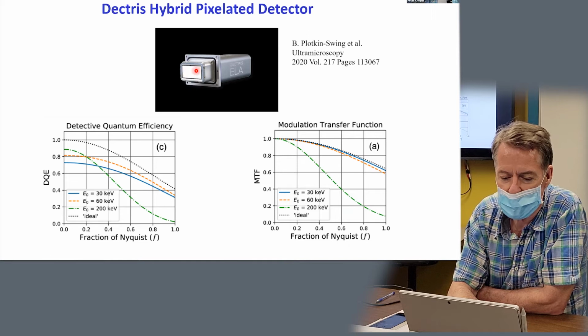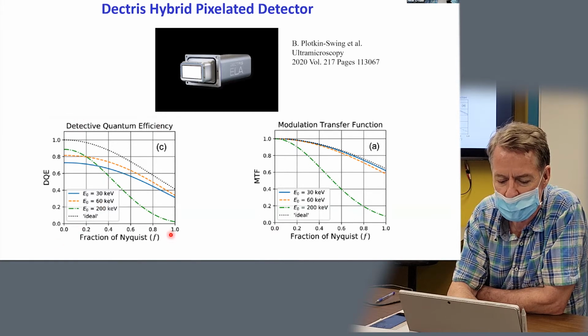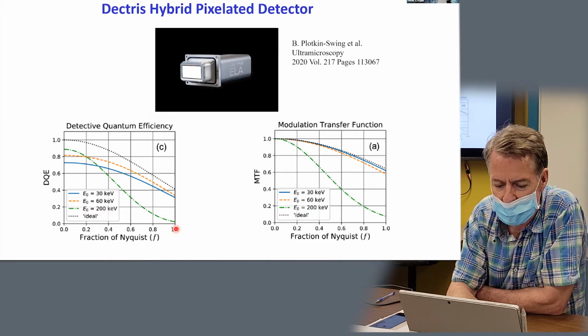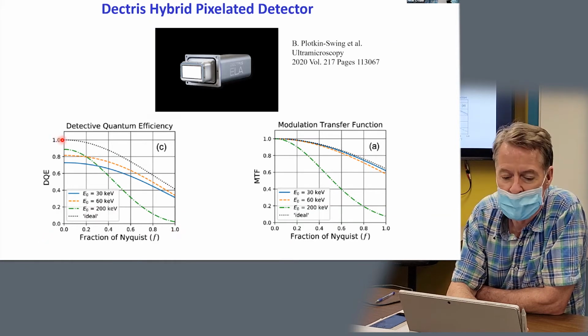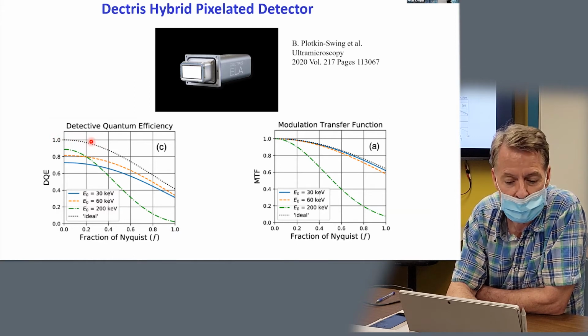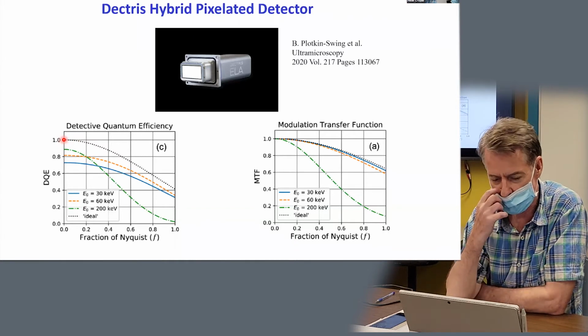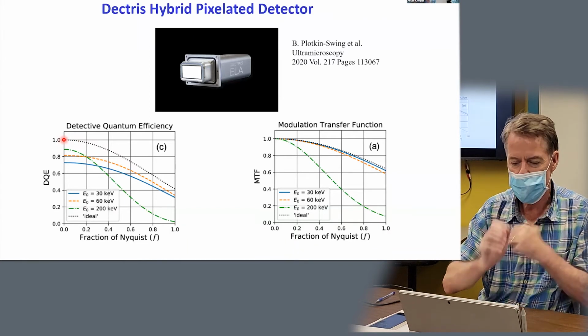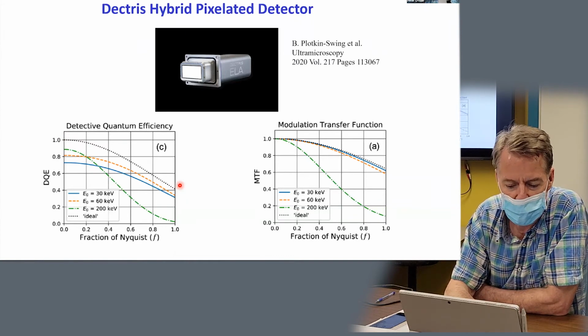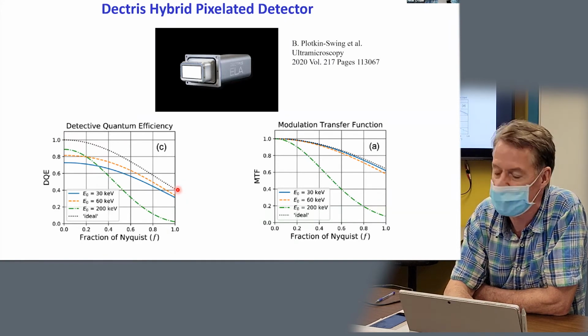This is the sensor element here. And again, a little bit of technical detail. This is a graph of the detector quantum efficiency as a function of spatial frequency, normalized to the Nyquist frequency. So Nyquist is over here. The black dotted curve is the theoretically best achievable ideal DQE, detector quantum efficiency. So it starts at 1 for spatial frequencies of about 0, and it drops to about 0.4 at Nyquist. Those of you that know, 0.4 at Nyquist is the best you can get.